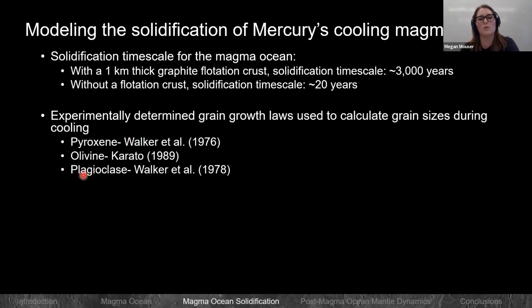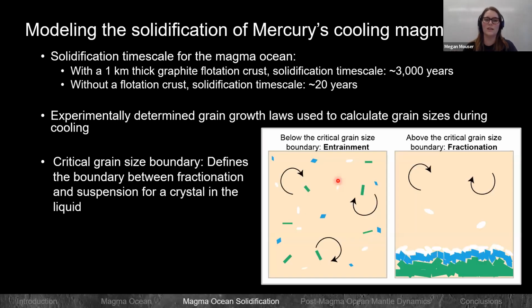So we utilized experimentally determined grain growth laws for olivine, pyroxene, and plagioclase, so the common mafic minerals. And essentially, we're estimating what could be the upper bound of these grain sizes that we could expect within the cooling magma ocean. So once you have this information, the next step is to essentially evaluate what type of crystallization process you could expect within this magma ocean. So we are utilizing this critical grain size boundary. So it's essentially a boundary that defines at which point your system goes from entrainment to fractionation.